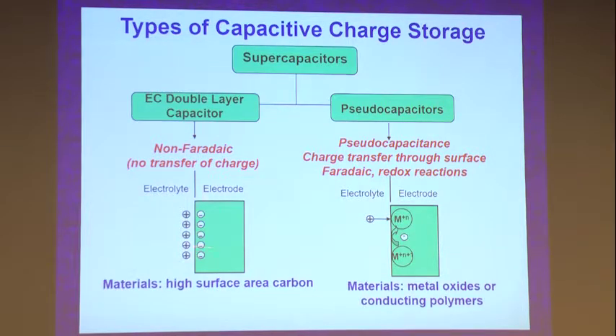So in this material, electrostatic repulsion between these ions is what limits the total capacity. But in this system, we're making neutral ion pairs. And so what limits the capacity is, just like in a battery, the density of redox active ions. But we now have a complex problem, which is to ask, how do we define surface redox? Is it the outer one atom layer? Is it the outer 1 nanometer? Maybe 10 nanometers. Maybe surface could be 100 nanometers. How do we define where a pseudocapacitor stops and where a battery begins?